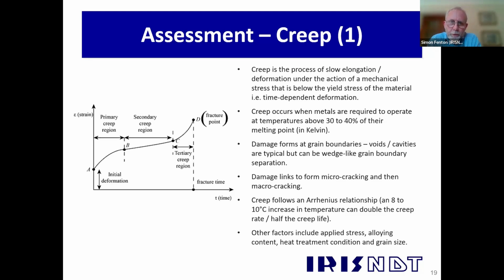So the damage itself forms on grain boundaries, and it's quite common in long-term creep to see voids and small cavities forming on the grain boundaries. But you can see this damage form as wedge-like grain boundary separation. This can occur when the stresses are very high and you get a short-term failure. And it can also occur at low temperature. We have something called low temperature creep crack growth. And that would tend to form wedges on the grain boundaries rather than cavities, the classic cavities. But all of this damage can be detected with the replica process.